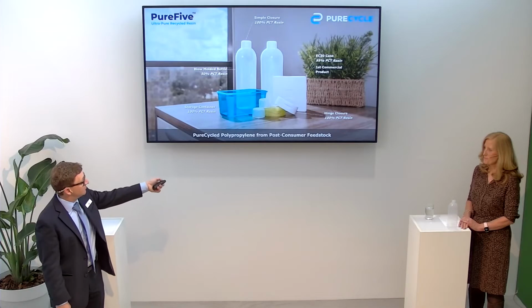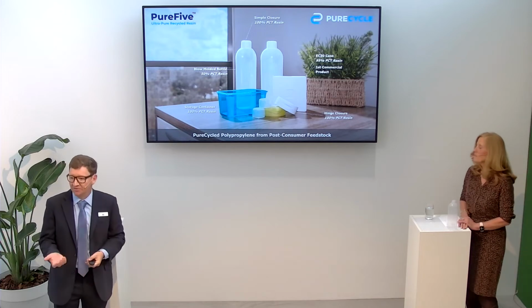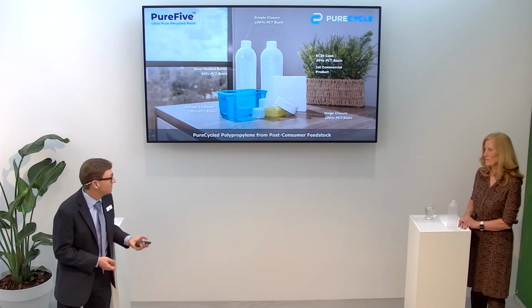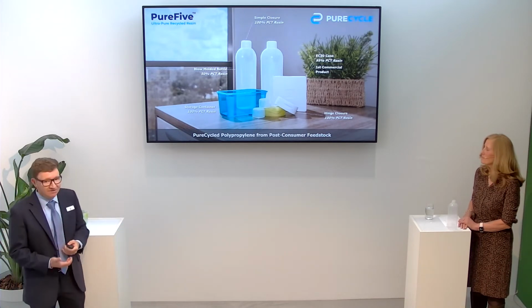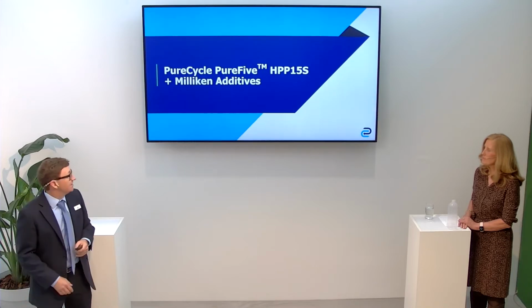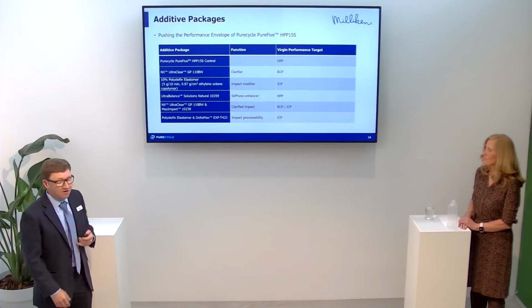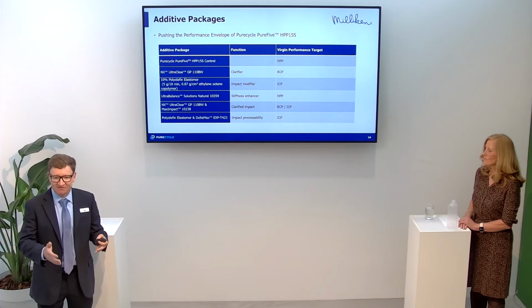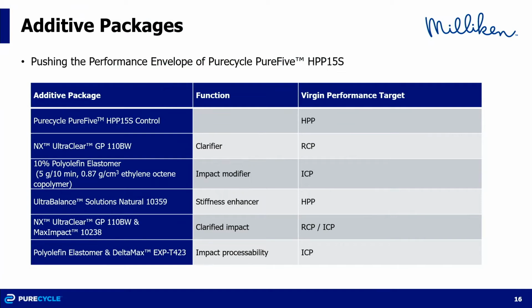You could see that the PureCycle material was able to make a hinge closure at 100% recycled content. So as Tamsin mentioned, we're really excited about this relationship, and our goal is to take that 15 melt flow or that single grade and push it into as many different property spaces as possible, right, to meet the demands and try to match properties of polypropylenes that are available in the market.